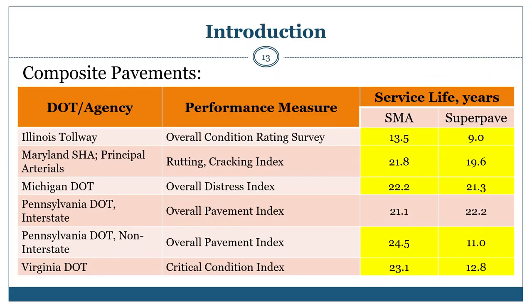For composite pavements, the cells highlighted in yellow show those studies or Departments of Transportation that have reported SMA mixtures to have longer service life in comparison to the Superpave dense graded mixes. As shown, the studies reported SMA mixtures have significantly higher service life in comparison to Superpave mixes on composite pavements.